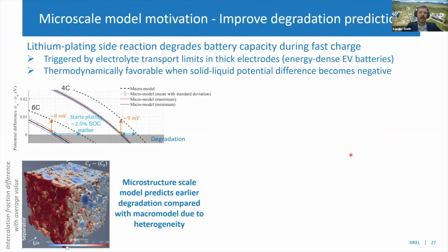Some of the things that we have done looking at heterogeneities, we've done comparisons with the macroscopic model. So that would be the dotted line here. And we're looking at the potential difference between the solid phase and electrolyte phase, which is what drives lithium plating when you drop below zero for that quantity. And we see that in the microstructure model, there's localized heterogeneities that cause the plating to occur about 2.5% state of charge earlier than what a macro-homogeneous model would predict.